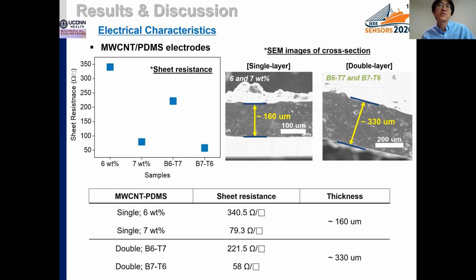In this study, we define B6 T7 or B7 T6 materials as a stacked double layer. Here, B6 means the bottom composite layer with 6% MWCNT, and T7 means the top composite layer with 7% MWCNT in the stacked double layer. B6 T7 or B7 T6 films show around 220 and 58 ohm/sq respectively, and the sheet resistance depends on the bottom layer. Also, as you can see in the SEM images of cross sections, the single layer has about 160 micrometers of thickness and the double layer around 330 micrometers, regardless of MWCNT concentrations.